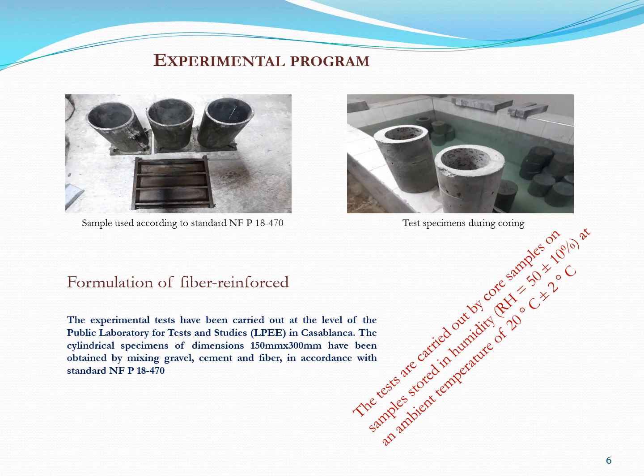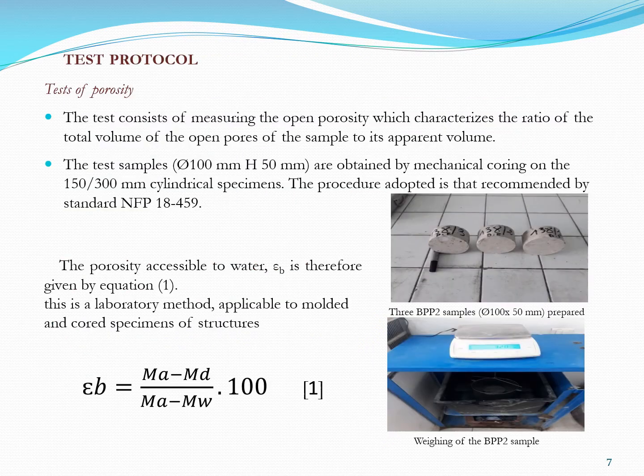First, a raw concrete mix was prepared to be considered as the reference, as shown in the figure. The same composition was used for the concrete matrix in all mixtures with polypropylene fiber. For the test protocol, the porosity test consists in measuring the open porosity, which characterizes the ratio of the total volume of the open pores of the sample to its apparent volume. The specimens shown in the figure are obtained by mechanical coring on the cylindrical specimens. The procedure adopted is that recommended by the standard, and the test consists of weighing the samples in air and then in a liquid of known density.